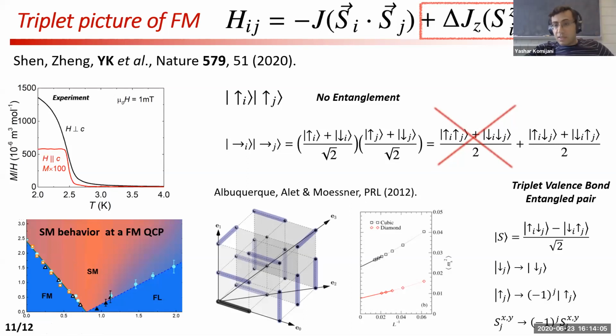And we can borrow the result by comparing these two states together. You can see that the only difference is that we need to go to every second site on this bipartite lattice and add a sign for the spin. And with this sign convention, their singlet coverings become M equal to 0 triplet coverings, and the staggered magnetization becomes a uniform magnetization.